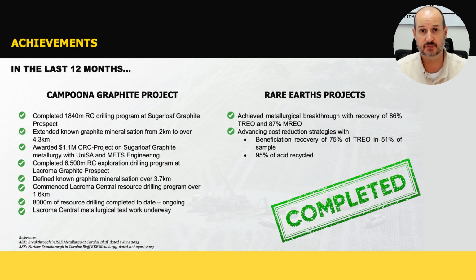On the rare earths project, we've achieved a metallurgical breakthrough on being able to extract those rare earths from the clay, where we got extraction rates of 86% of the total rare earths and 87% of those more valuable magnet rare earths. Now, the process that we use to extract it, we're not 100% confident that is yet an economic process that can be undertaken. So we're working on lowering the costs of that extraction technique.